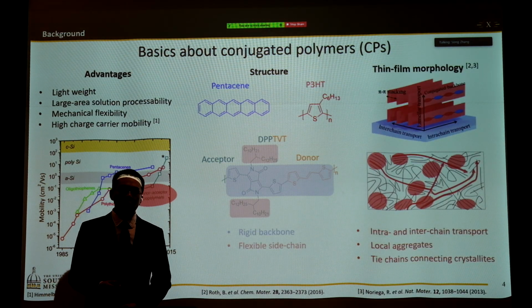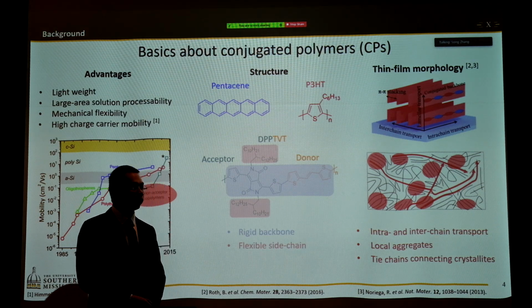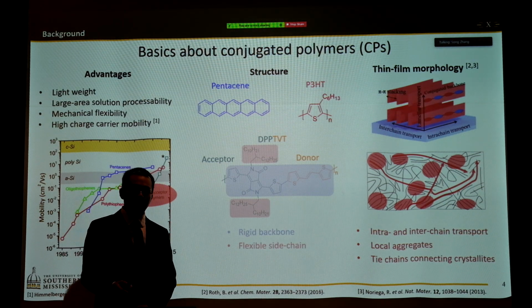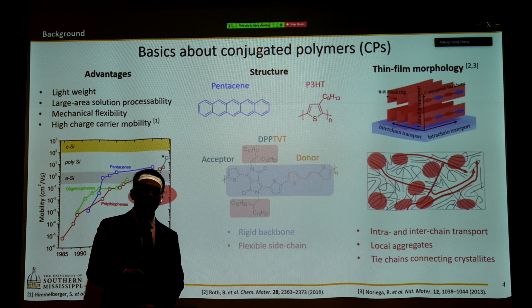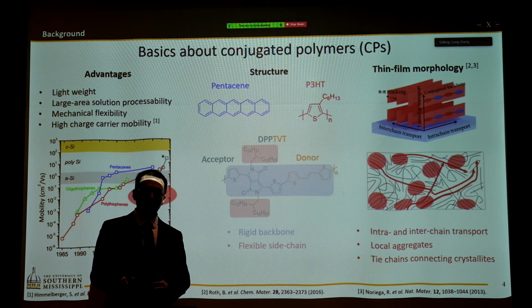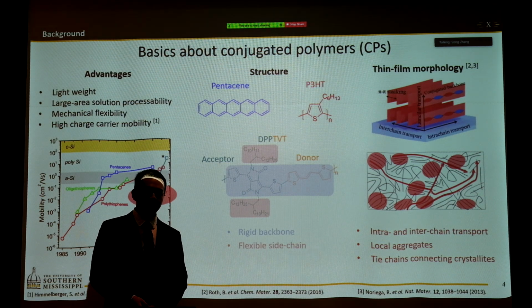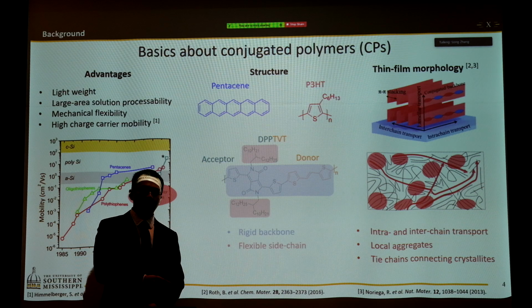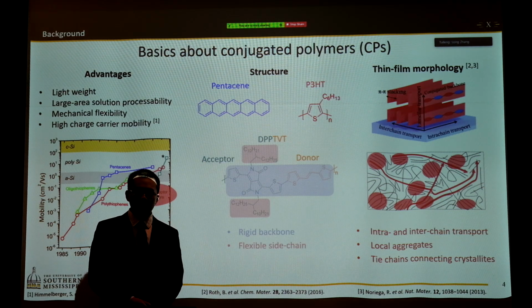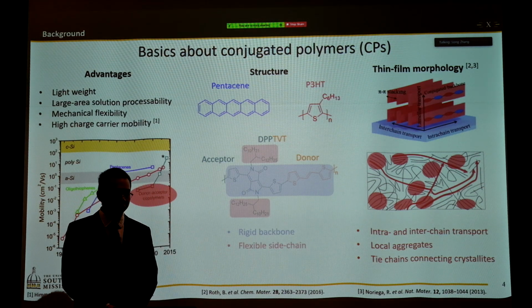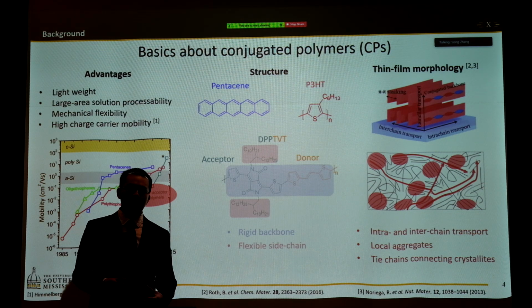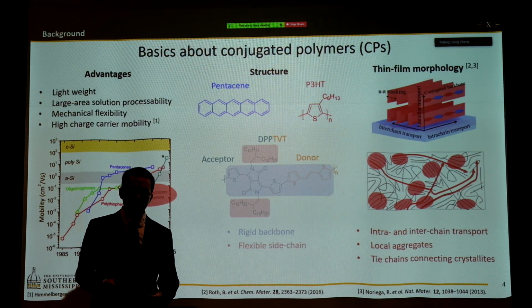And the crystalline structure is rather complicated. For example, we have charge transport along the polymer backbone direction, and along the backbone, there is alternating donor and acceptor. The backbones can also pi-pi interact with each other and have this intra-chain charge transport pathway, and charge can hop between backbone and backbone. Along the vertical direction is the lamellar direction, since polymer side chains are not conductive to electrons. That's why the charge does not transport through that direction.